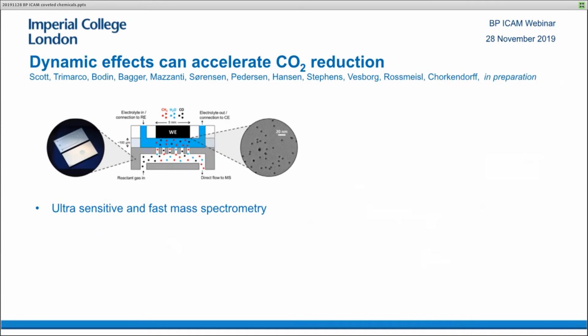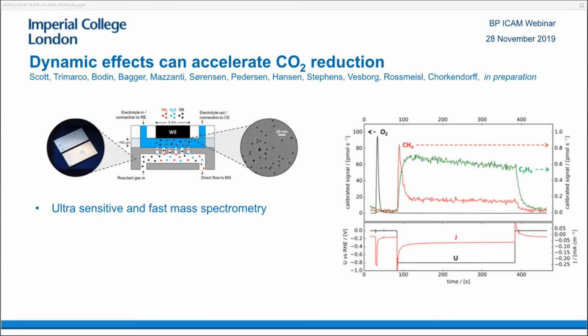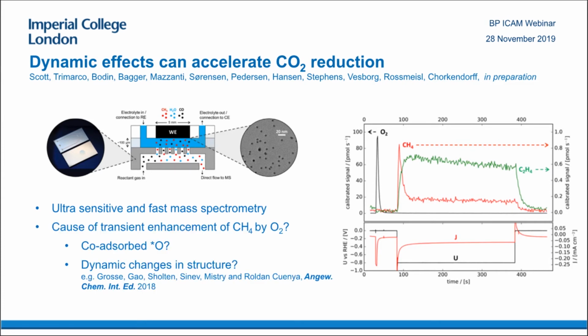So far I've been looking at surface effects, changing the surface to accelerate reactions. Another way you can do it is by looking at dynamic effects. At my former institution, my colleagues developed a very novel electrochemical mass spectrometry technique. I'm very excited because we're going to get one of these at Imperial College. What you can essentially do is measure gases with really high sensitivity, picomole per second sensitivity.